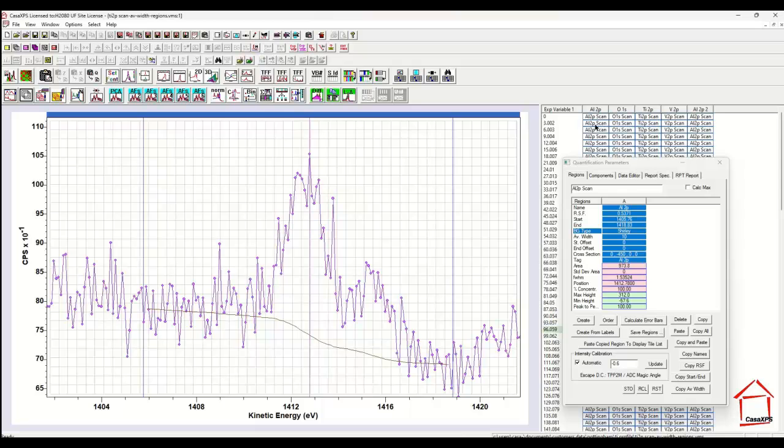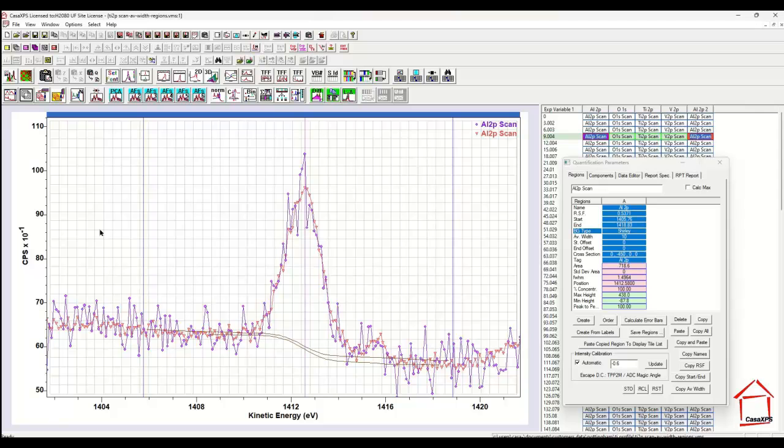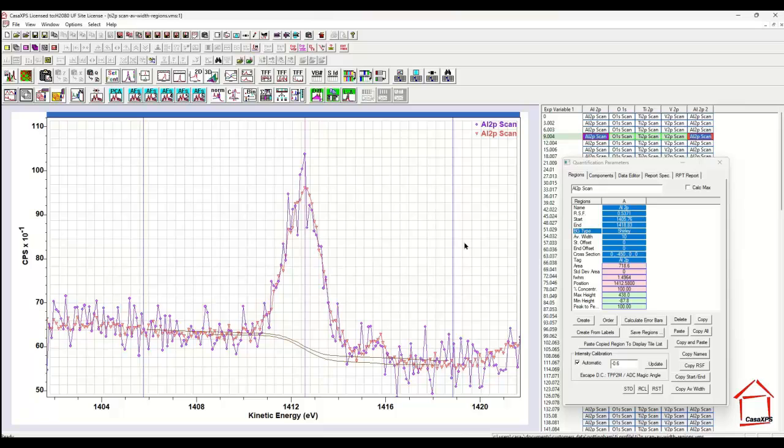However, if I overlay a noise reduced versus a spectrum that has not been processed, you can see that there is a clear correlation between the noisy data and the PCA data. And yes, it does highlight the oxide and it also shows that there might be some trace of a metal even at this early stage.